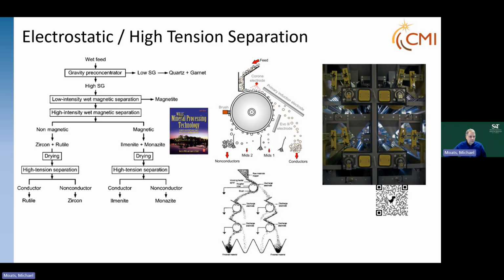In high tension or electrostatic separation, essentially, we have a corona electrode which charges all the particles. There's a conductive drum, and the particles that are conductive lose their charge and fall off the drum as it's spinning. The non-conductive do not lose their charge and eventually come around and either form non-conductive concentrates or some middlings streams which are reprocessed. You usually put rolls in vertically. So here you can see some high tension rolls. Basically, if you look, here's conductive, here's conductive, here's conductive, and so we end up with a concentrate that has three times the conductive material. And this is how we make a separation.